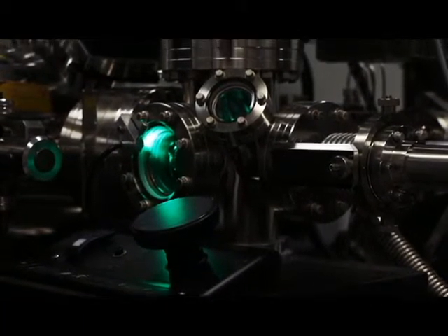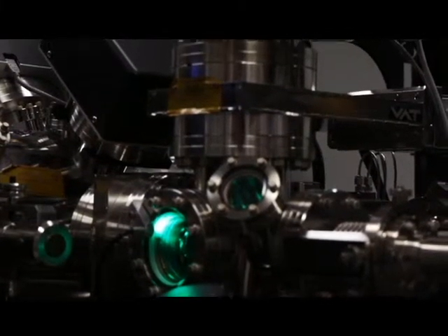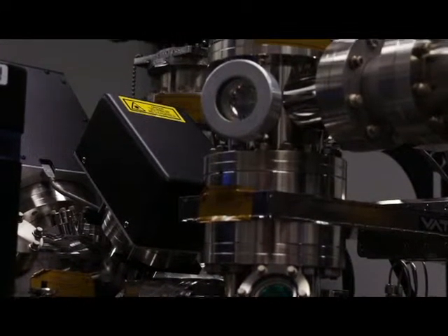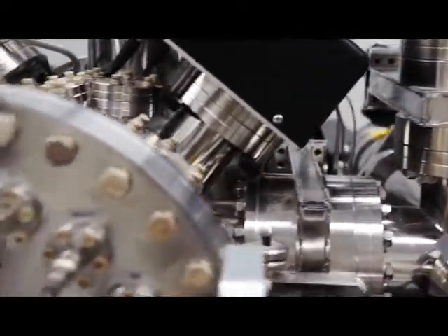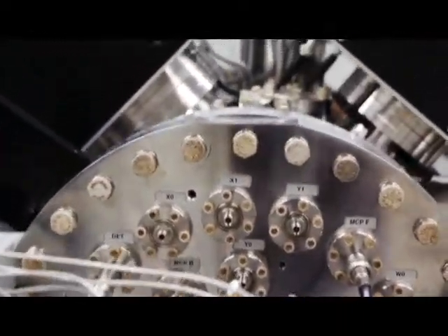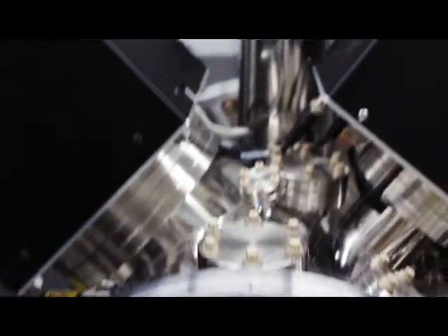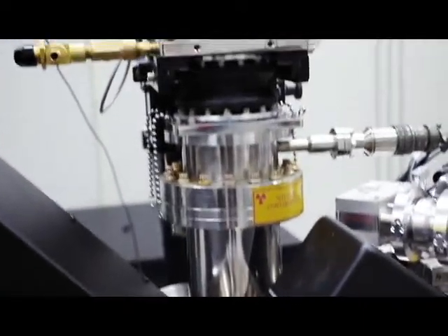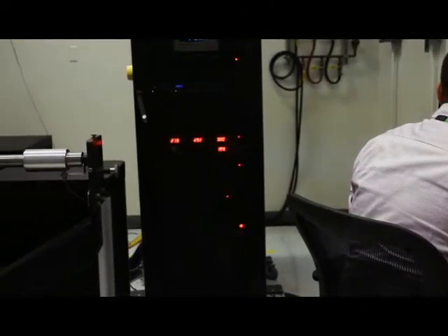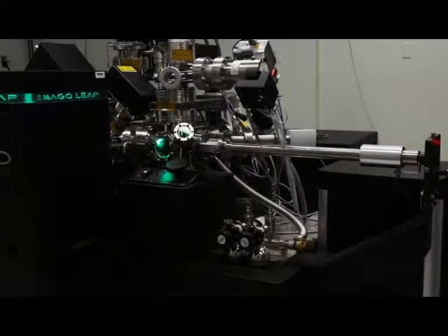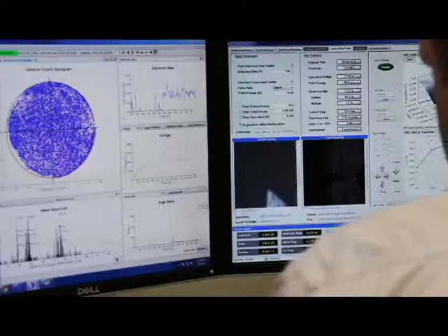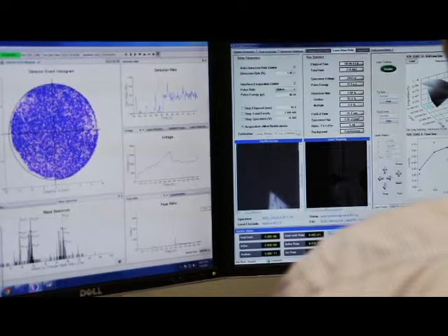So it really does help us look at things like precipitates and segregations to grain boundaries, where we can get profiles of how the elements within the material actually behave, and then we can do that for different conditions and get a bigger picture of what's going on. And then because it's almost atomic scale, we can give that feedback into modelers who can then scale up the